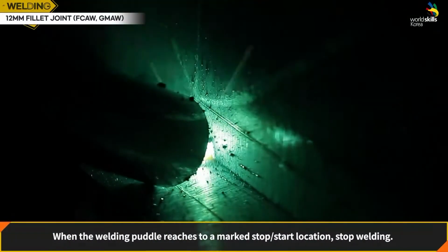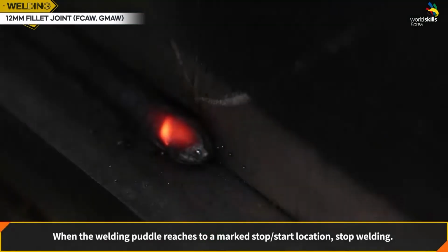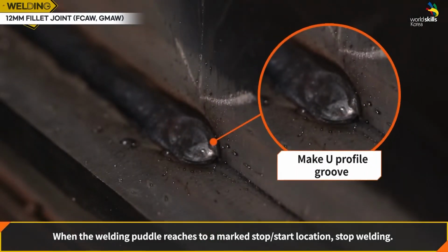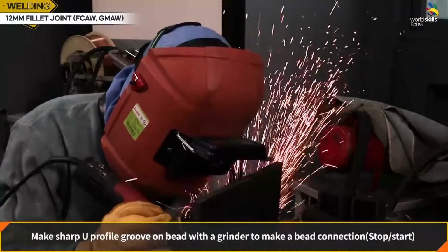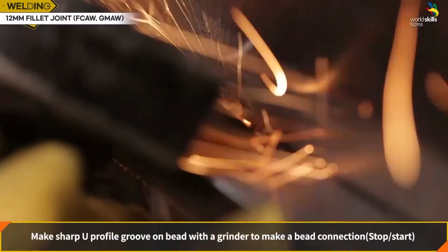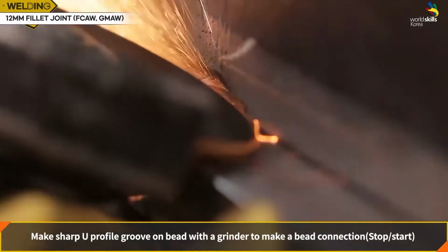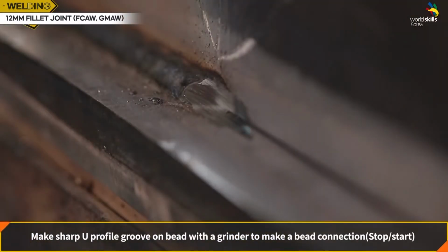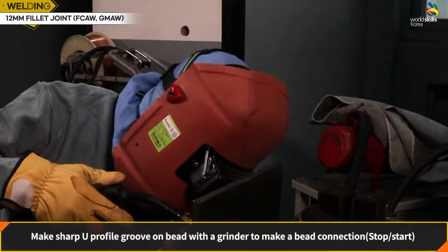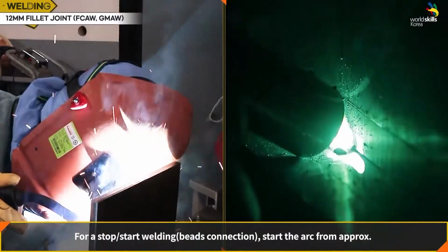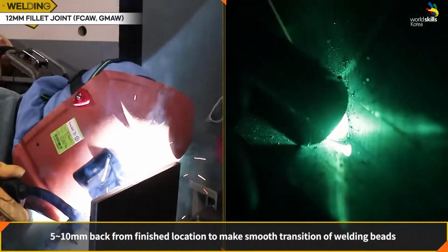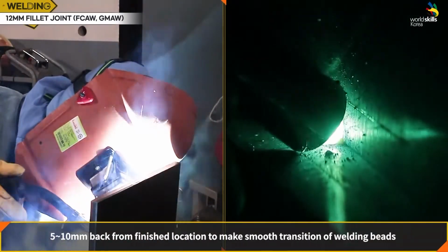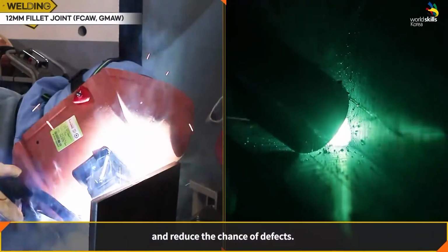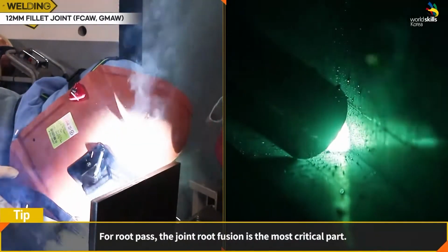When the welding puddle reaches a marked stop-start location, stop welding. Make a sharp U-profile groove on the bead with a grinder to make a bead connection, stop-start. For a stop-start welding, beads connection, start the arc from approximately 5 to 10 mm back from the finished location to make a smooth transition of welding beads and reduce the chance of defects.